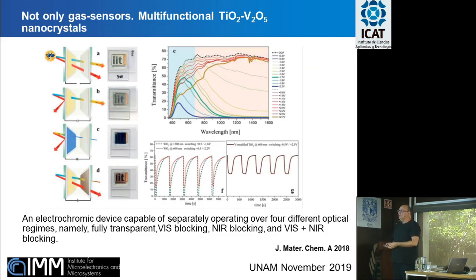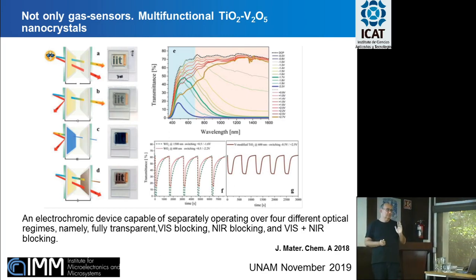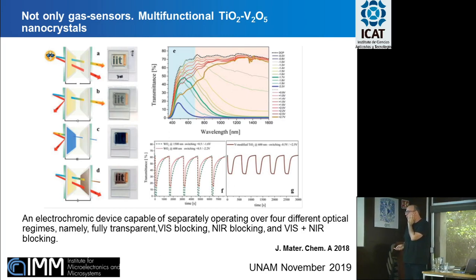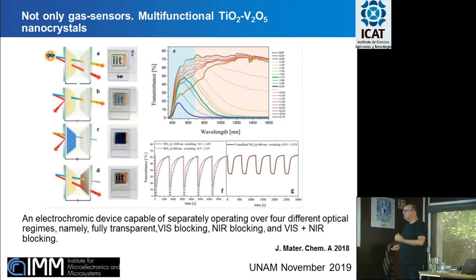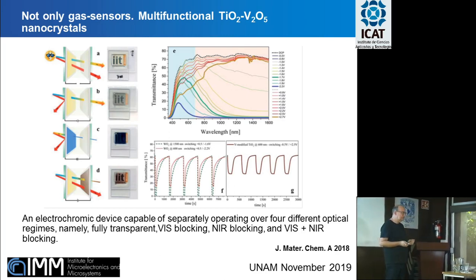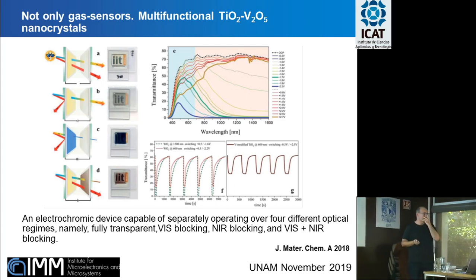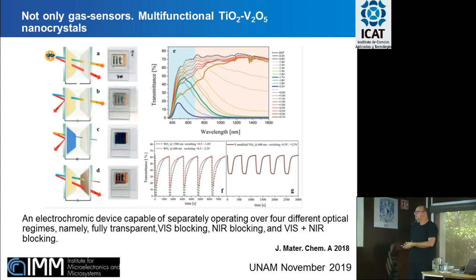Once again, another application. We can couple our titanium vanadium nanocrystals with tungsten oxide nanocrystals in a multi-layer configuration, where we can prepare an electrochromic device capable of separately operating over 4 different optical regimes, which is fully transparent, vis blocking, it is blocking the visible light, near infrared blocking, and completely blocking both kinds of radiation, which means that these coupled materials could be used in electrochromic windows for controlling the energy exchange of environments with the external atmosphere.